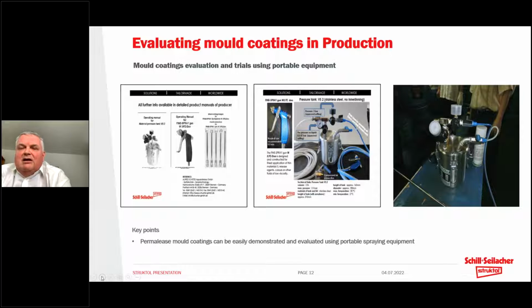So we can fill in a 5 litre, self-contained vessel. We can pressurize it with the airline, we can adjust the pressure, and then we use a fine nozzle gun, typically a 0.4 millimeter diameter, in this case air-assisted gun, to spray the mold and carry out the trial. A number of extension lances are available, so it's practically very easy to reach every kind of mold and carry out trials or to adopt this kind of technology in production. Next slide, please.